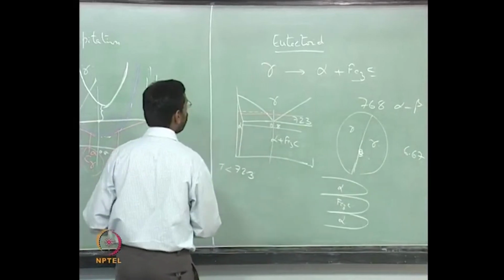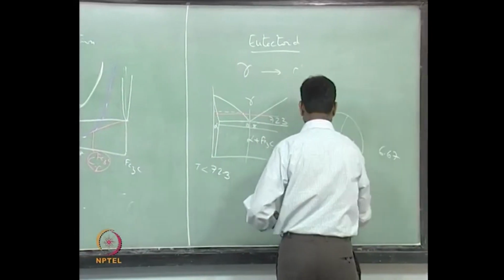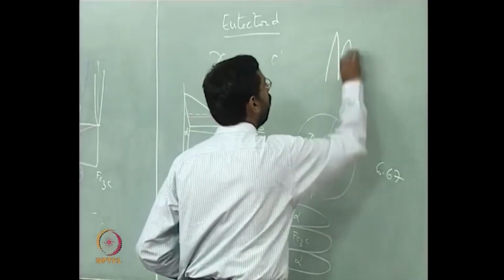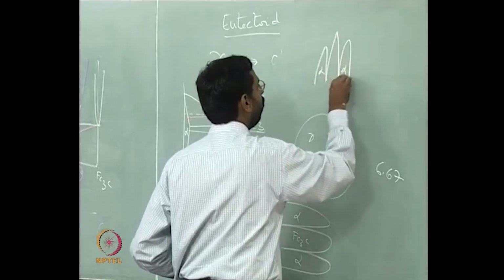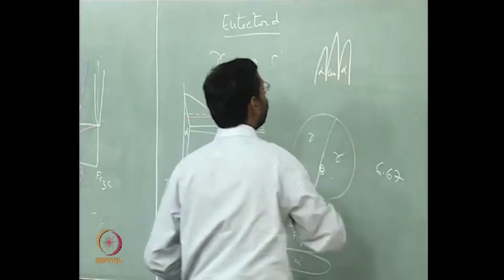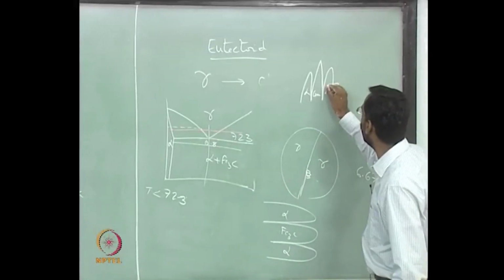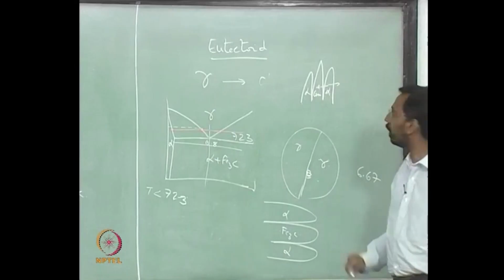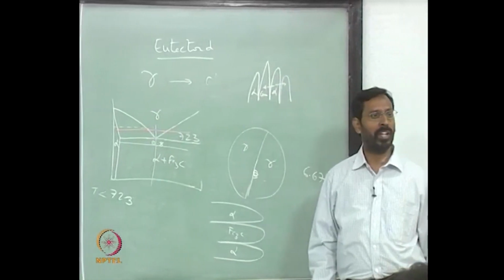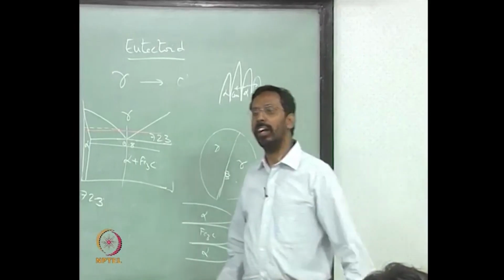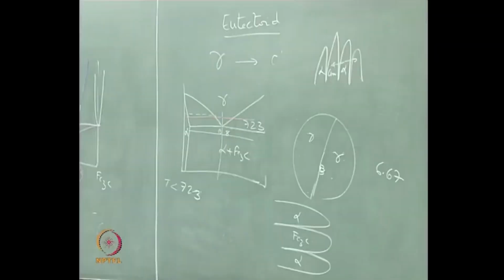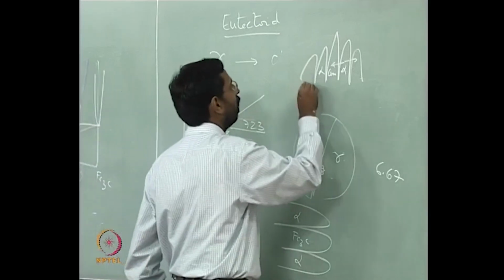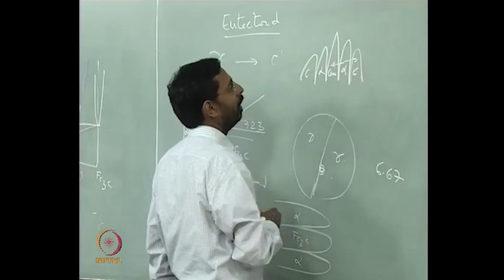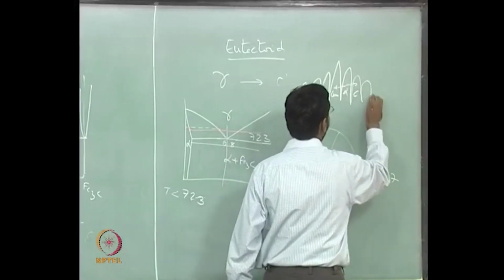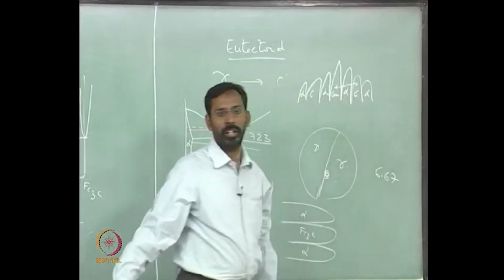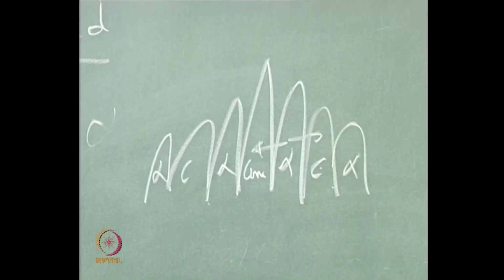So, if I draw it in a bigger fashion, the moment a cementite comes out, okay, a ferrite is there, this is alpha, this is alpha, this is Fe3C, call it as cementite. So, the carbon is rejected out of this region in both the directions. Once it is rejected out, then again you will see a cementite coming out here, and this happens and it grows laterally with alternate layers of cementite, and then again obviously alpha, and this whole thing starts growing perpendicular to the grain boundary.